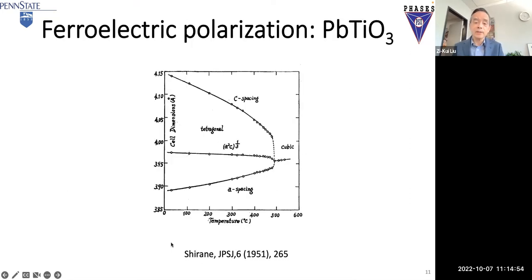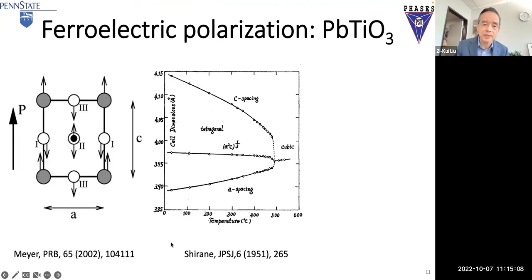So again, before I did the bird and the cage experiment, now we do a real materials experiment. We take the material lead titanate, which is a ferroelectric material. We know that at low temperature, you measure it by X-ray measurements and you get the c/a ratio, so it's tetragonal. The titanium atom moves away from the center, and you get a polarization. So at low temperature, it is ferroelectric, polarized tetragonal.